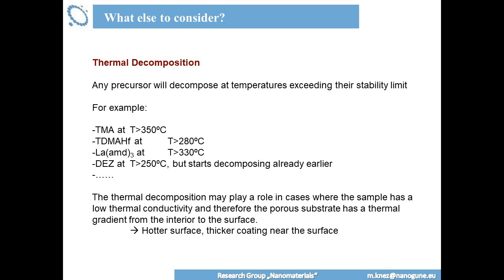And well, it has to do with a little bit of parasitic CVD as well with the diethyl zinc. We did some DFT calculations some time ago that DEZ already at 100 degrees has a certain self-decomposition which results in some zinc radicals or ethyl zinc radicals flying around. So keep this in mind, that zinc is not really that stable as it's supposed to be. Just a side information.